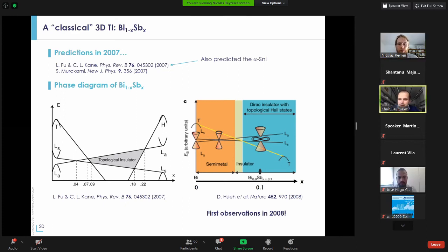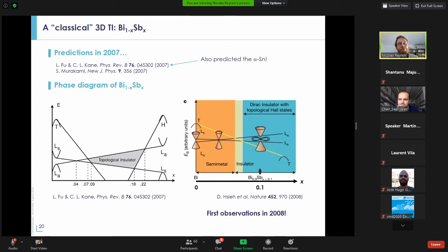Okay, good, thank you. The second question is from Marcos Guimaraes. He's asking whether the disappearance of the Dirac cone is due to material intermixing, disorder, or doping. From what I see, in the case of MgO, at least we can see by X-ray absorption spectroscopy that the tin is oxidized. So maybe the cone is then hidden below this oxide layer of the tin. This we cannot say. What we see at least is that we don't observe any signature of the Dirac cone experimentally.